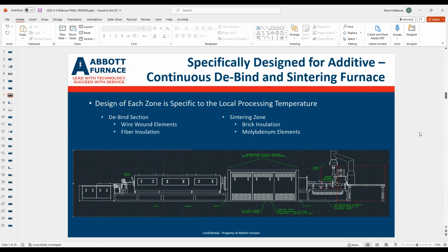So we can reap the benefits of that lower cost construction in that area to lower the overall capital costs. We're no longer looking at the conventional pusher furnace that's all brick and moly elements. We only put the brick and the moly into the area next after the debind area. There's a small area that is designed to take us up to that 1550 temperature for doing things such as the 316 or the 17-4. And then we exit out into a cooling area, and the boats then travel out the furnace to the far right and are unloaded, and the boat is then cycled back up to the front again.